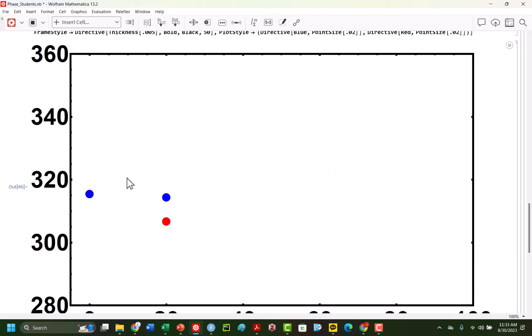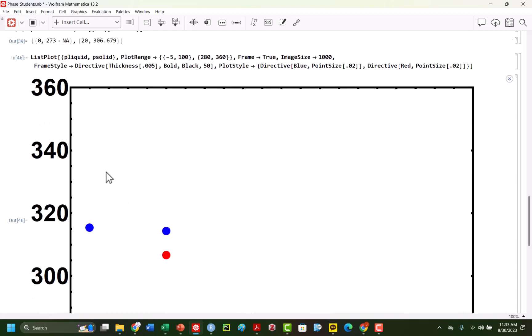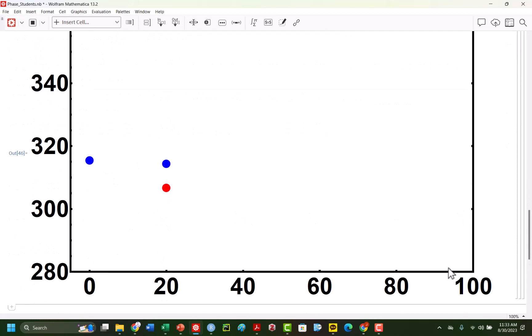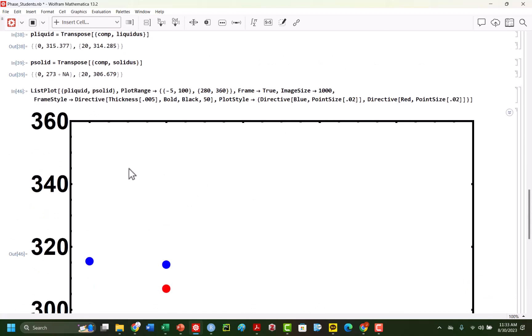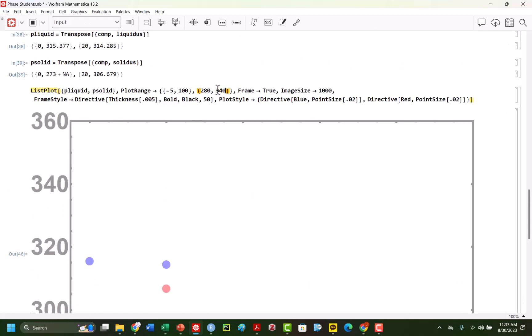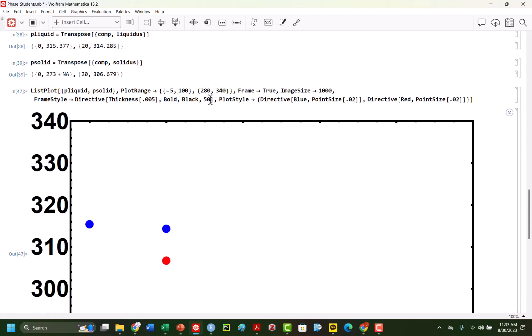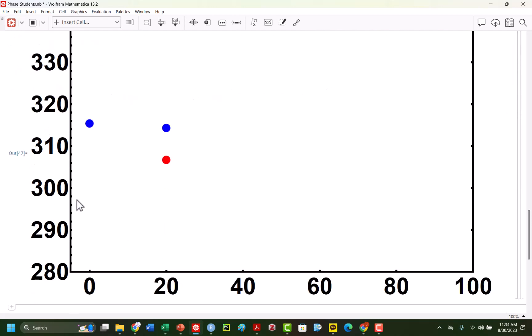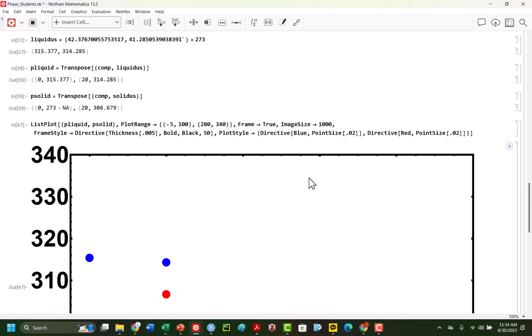so we're seeing essentially here your liquidus, and then your solidus will effectively, be over here. So you're going to make essentially this phase diagram, and you will plot this for all the different compositions. You will identify any invariants, any kind of distinguishing features. We may zoom in a little bit here, just so you can see some cool features. So you can kind of see. So we should always kind of start off at the edges, highest melting point, and they should be lower liquidus, and then same thing over here. But we'll see that in those features.